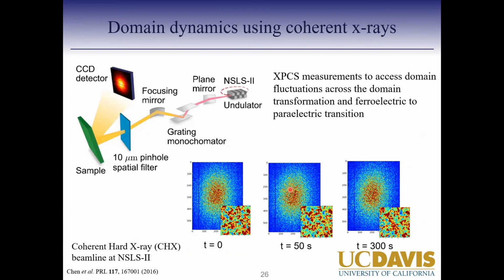And the key factor here is coherence. If you have coherent X-rays coming out of the synchrotron, as you diffract from the sample, whichever Bragg peak you are sitting at, that Bragg peak looks more speckly. If you have any inhomogeneities in the sample, any sort of domain structure, coherent X-rays would scatter through that and acquire a phase depending upon what sort of inhomogeneities you have in your material. As they acquire a phase, they'll go through constructive and destructive interference within itself. And that interference would then show up in your Bragg peak, where certain regions are very bright and certain regions are really dark. So these are red areas which are bright and blue areas which are dark.